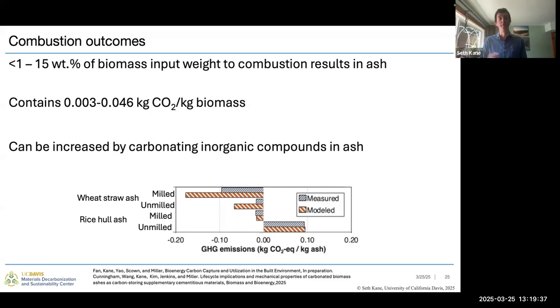It was able to increase that from that maximum of 0.046 we see of just CO2 present in the ashes to about minus 0.1 kilogram of stored CO2. This is still not quite up to the theoretical maximum, but that's dependent a little bit on exact process design and optimization, things like that.